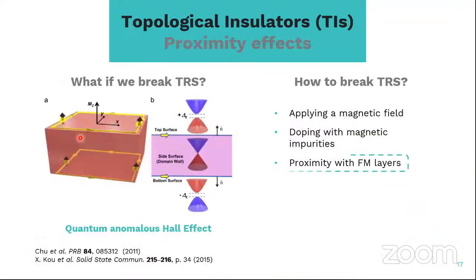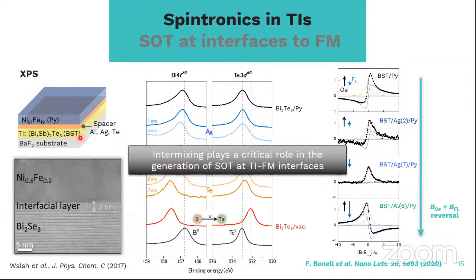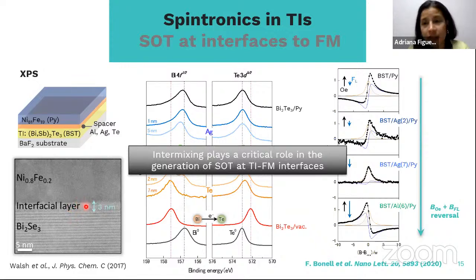One, regarding this interdiffusion of any metal that you have in contact with the TI, how do you consider that for the quantification of the spin orbit torque efficiency? I mean, do you consider that it is just on this topological insulator or this new interdiffusion layer with selenium and tellurium? Yeah. So as you say, there is. And also it has been reported there is interdiffusion, and this is what we wanted to explore.